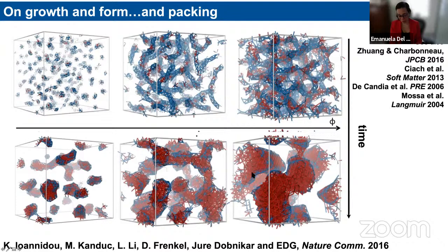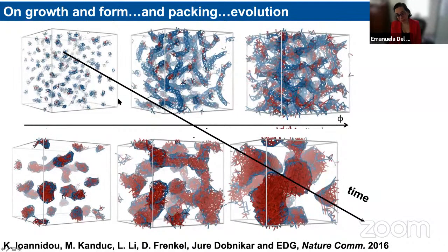So if we think about the evolution of the interaction over time now, we realize that what is happening in cement is something like that. You start with interactions that allow for a fast early stage percolation of the material, which allows for some pore size that can be controlled, and that guarantees some development of mechanical properties, maybe weak, but really at early stages. And then as the interactions evolve, you switch to interactions that favor the local densification of the gels. So that's how precipitation can continuously occur.